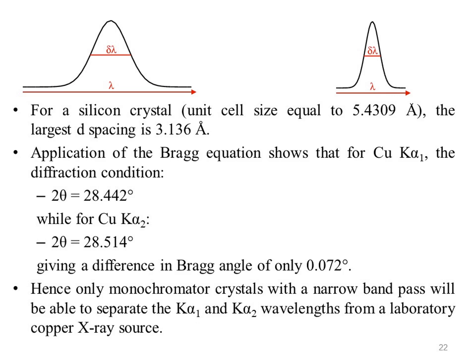copper K alpha 1, the diffraction condition will be satisfied for 2 theta equal to 28.442 degree, while for copper K alpha 2, it will be satisfied for 2 theta equal to 28.514 degree, giving a difference in Bragg angle of only 0.072 degree. Hence, only monochromator crystals with a narrow band pass, for example silicon, will be able to separate the K alpha 1 and K alpha 2 wavelength from a laboratory copper X-ray source.